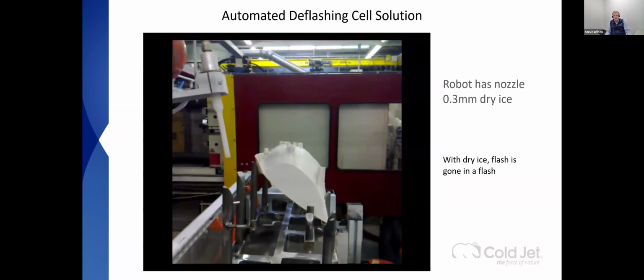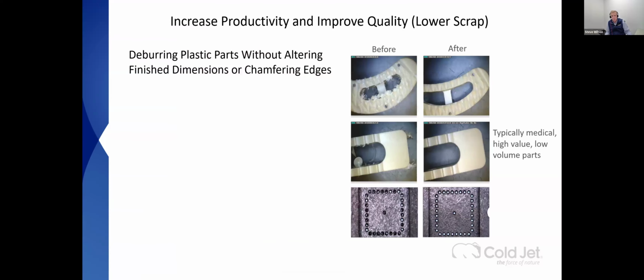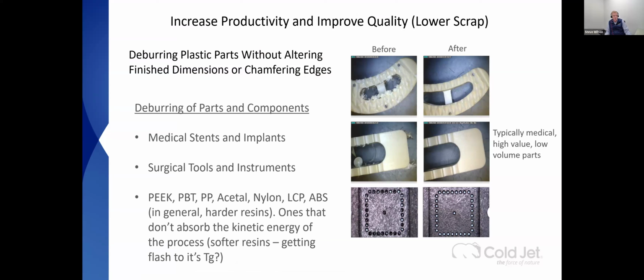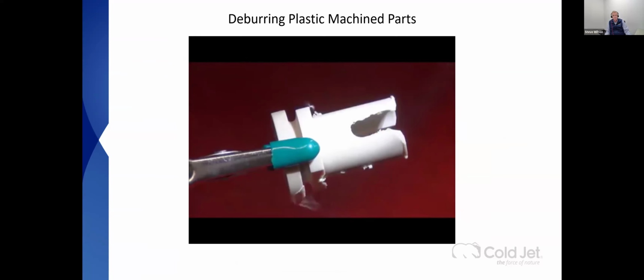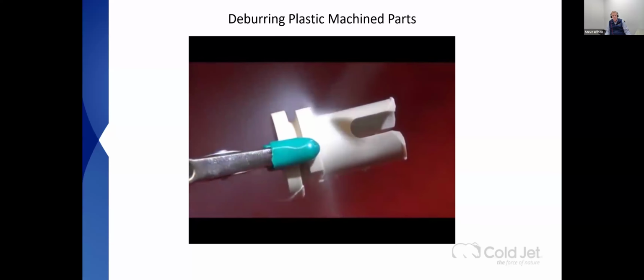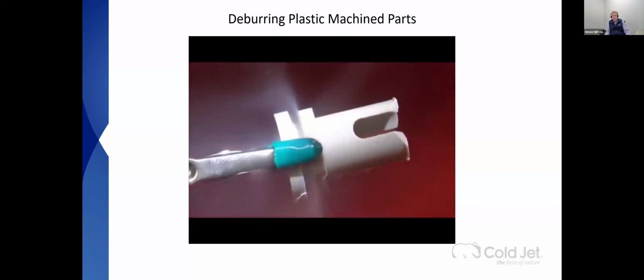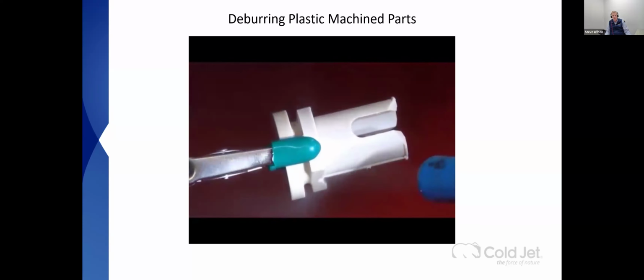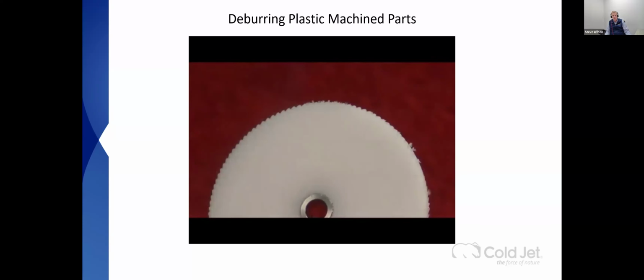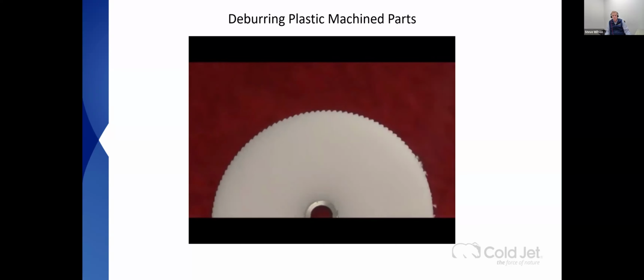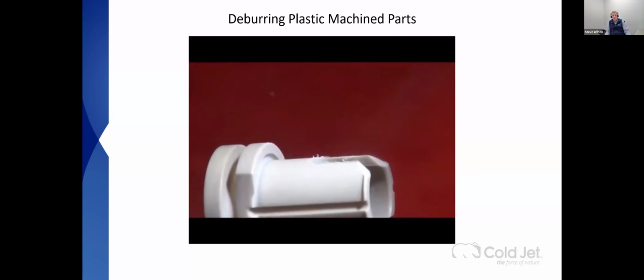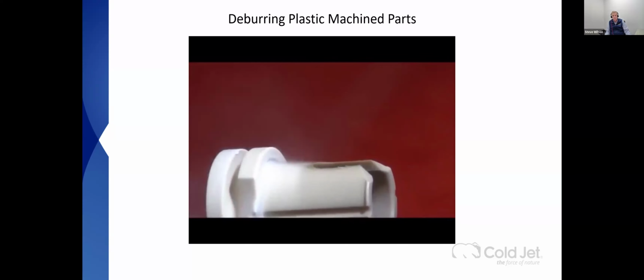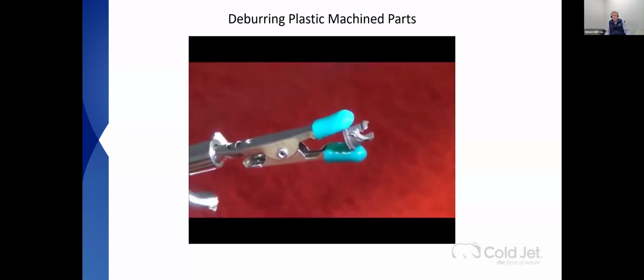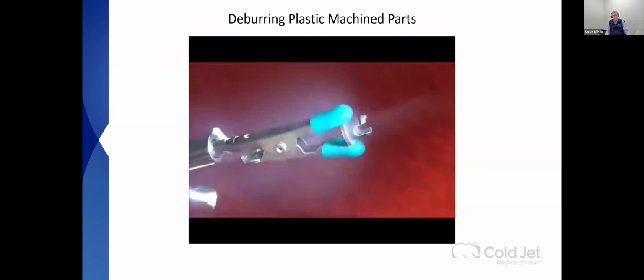We have flash, mostly thermoset parts. If you machine parts, we can take burrs off as well. They're typically high value, low volume parts, medical parts usually, PEEK and a variety of materials. This is what it looks like to remove burrs from various polymers. The burrs do remove pretty much in a flash. I'll let it go for a couple seconds. There's a couple different types of burrs on here that are being removed. The perimeter of these gears, you can see the dry ice is removing burrs without altering the machine finishes or chamfering the edges. You're simply removing the excess unwanted material and saving that part.